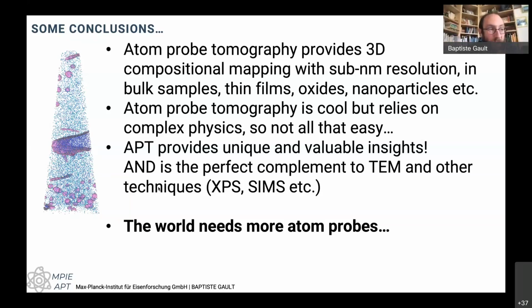And yes, we sometimes can look at site occupancy, so whether an atom is sitting, sorry, as substitutional or interstitial. We need to be very careful when we prepare specimens for this, because we need to be along a series of planes where we sort of know there might be some ordering taking place, for example, or at least along which we should be able to accurately measure the interplanar distance and the position of these atoms in the z-axis.